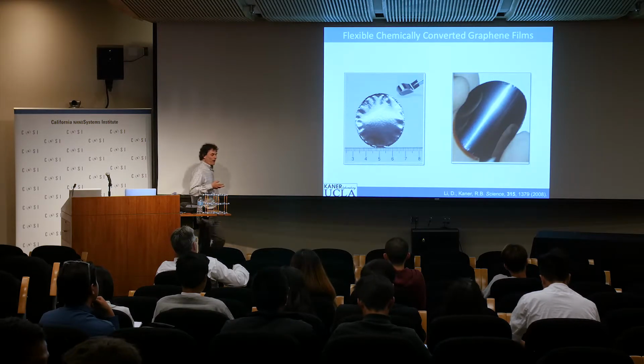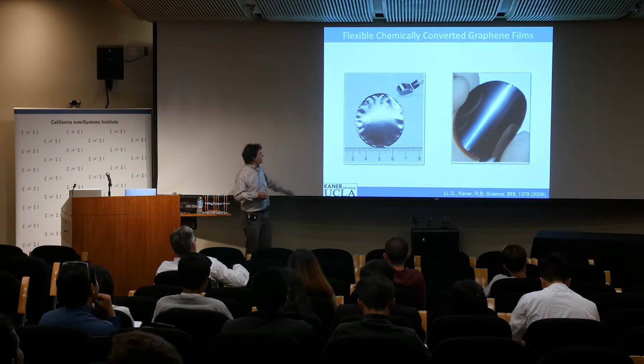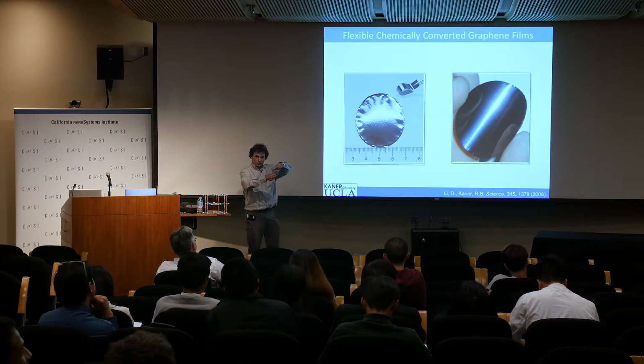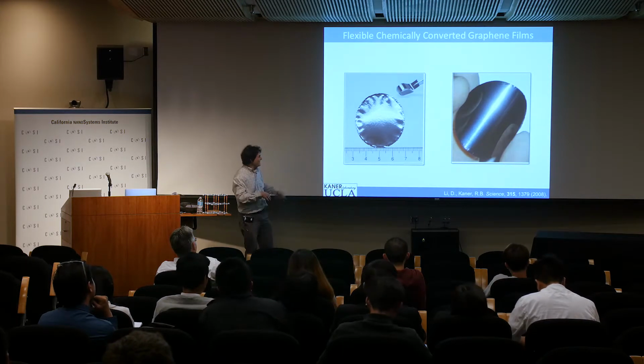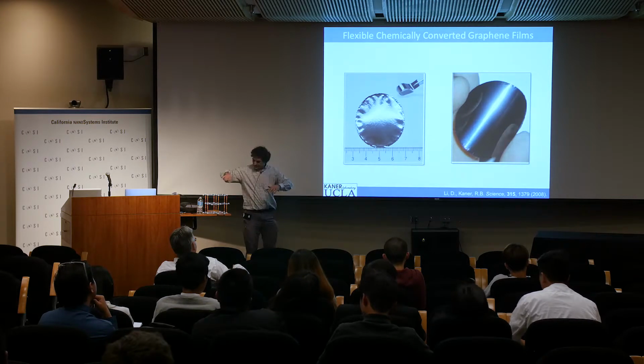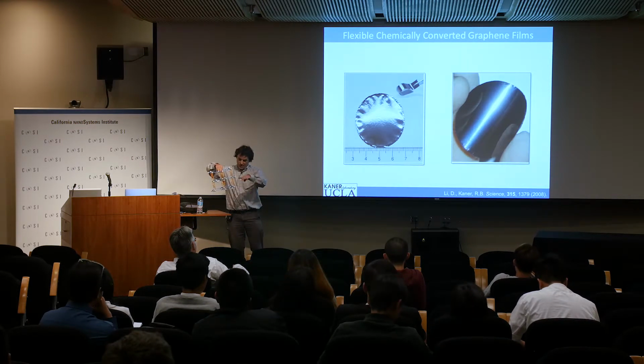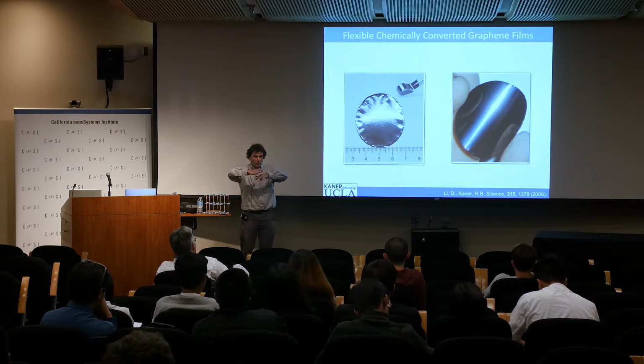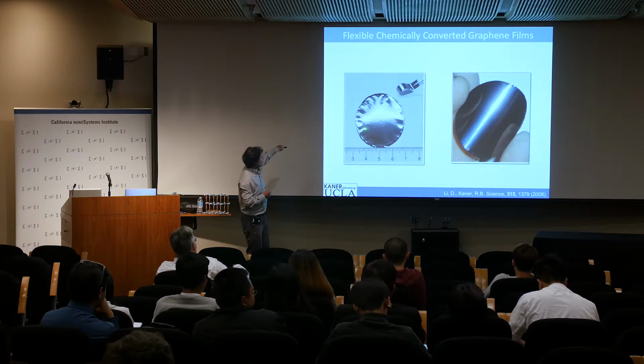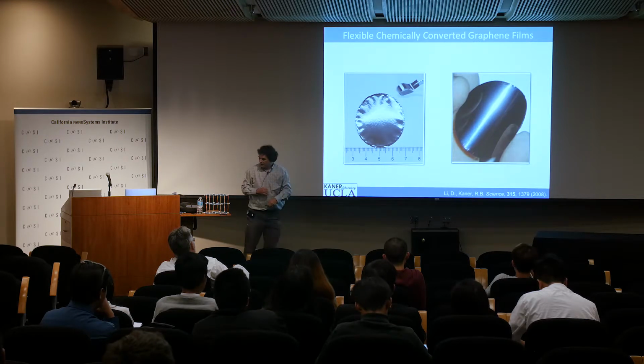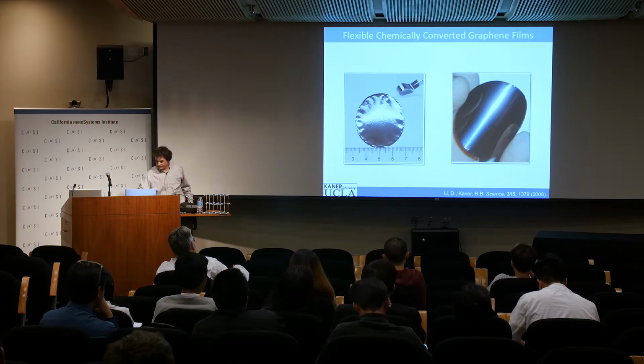Once you've made this graphene, you can stack it up. And here's graphene paper. We just ran it through filter paper, trapped all these layers. It's not graphite because graphite is actually three-dimensionally ordered. They go A, B, A, B. These are just random graphene sheets. But they're thick enough that you can actually fold them. You can see your reflection. This is a paper from Science a few years ago that we put together.